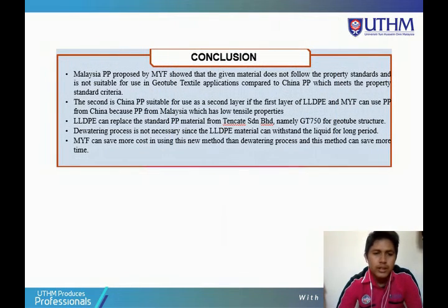For the conclusion, the Malaysia PP proposed by MyFlexitank showed that the given material does not follow the property standard and is not suitable for use in Geotube textile application, compared to China PP which meets the property standard criteria. The second is that China PP is suitable for use as a second layer if the first layer is LLDPE, and MyFlexitank can use PP from China because PP from Malaysia has low tensile properties.